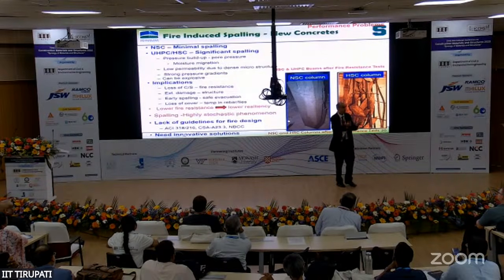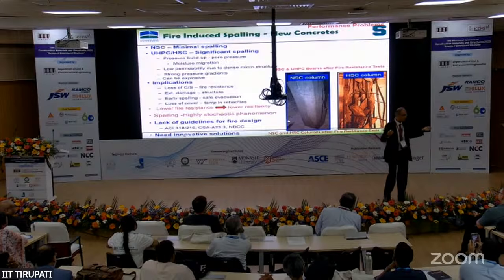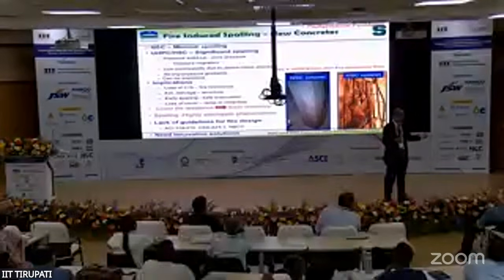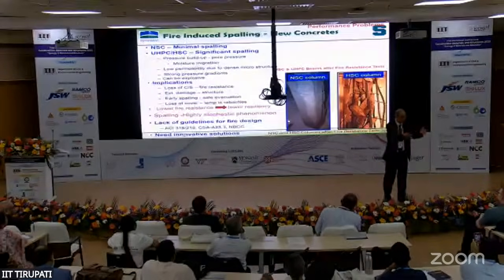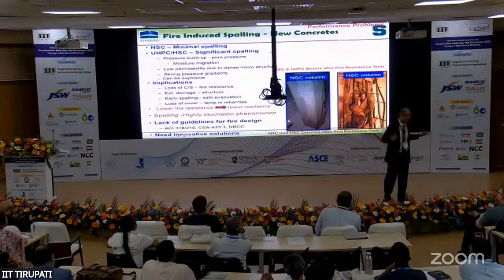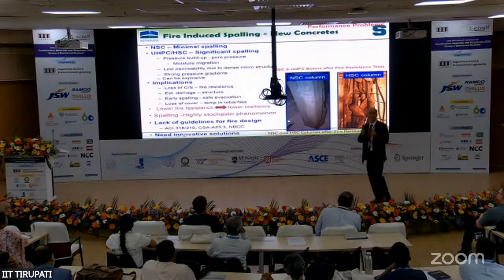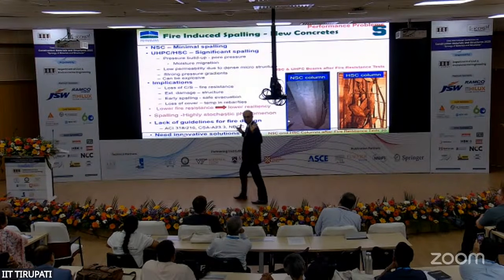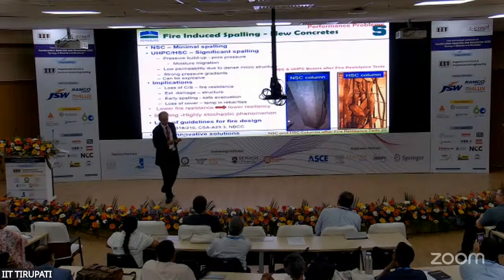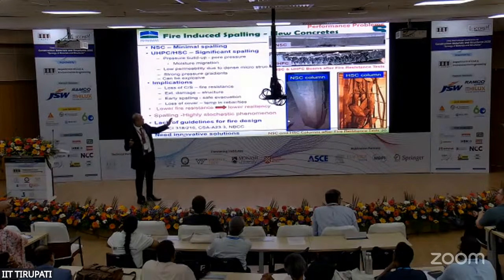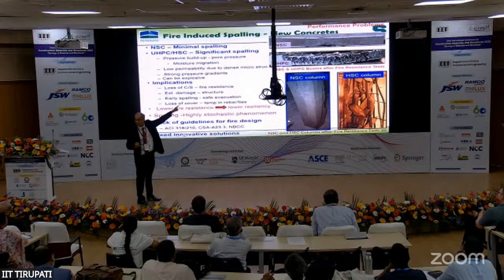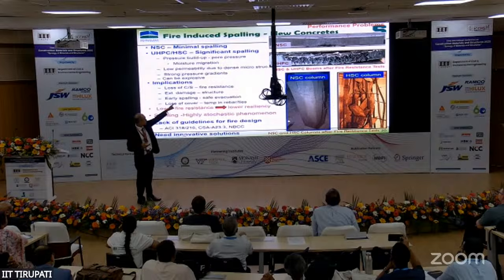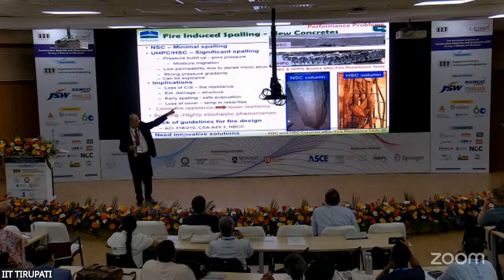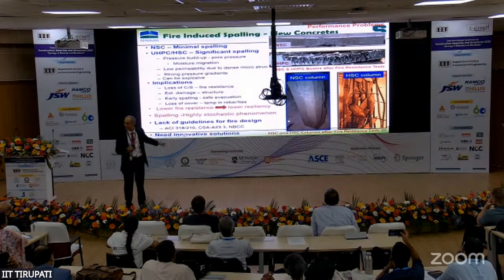So that steam converts itself into pressure, tensile stress. In fact, if you increase the compressive strength but not the tensile strength very much, when the tensile stress exceeds tensile strength, which is dropping with temperature, boom, boom, boom, popcorn, right? So that's what happens. And it comes out as bullets. That's UHPC beams. You can see on the top, conventional normal strength at 3 hours. After about 76 minutes, UHPC, okay?